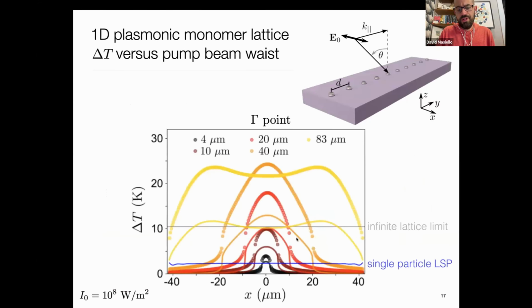So you're looking at two different temperature increases. One, progressively blowing out the width, driving the system at the surface lattice resonance. And I want you to contrast that back to this blue curve, which is just the single particle LSP, driving at the single particle LSP resonance across the same array, using the exact same incident intensity of light. So you can see that there's a massive increase in temperature rise by driving the system at the collective surface lattice resonance rather than at the single particle resonance.